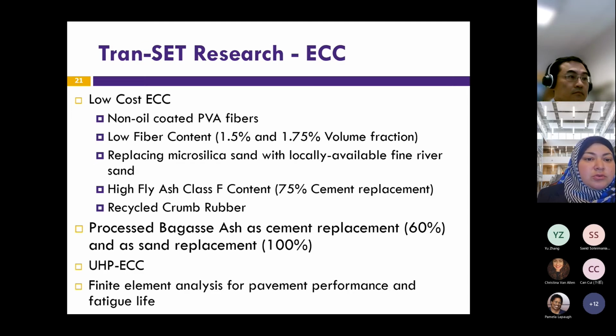So what did we do to solve these problems? At TRANSIT, we started working on solutions to make this technology implementable. So we started by looking, can we bring down the cost of ECC? We wanted to change the fibers. So can we use non-oil coated fibers, for example, because they are much cheaper than oil coated? And we wanted to reduce the fiber content. Instead of using 2%, go to 1.5 or 1.75 volume fraction.